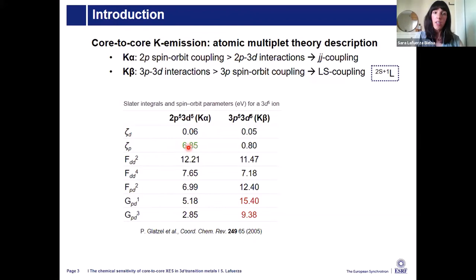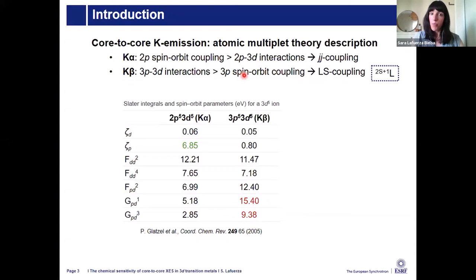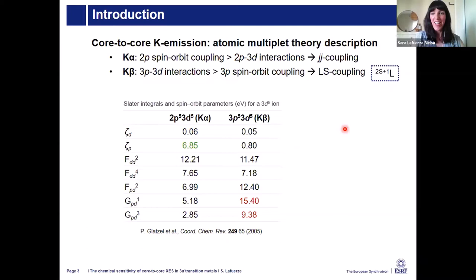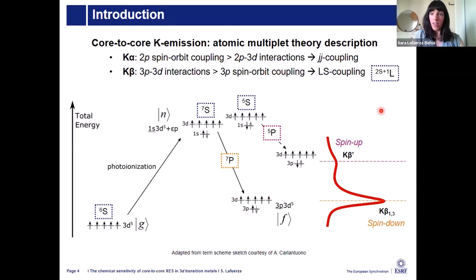In K-alpha, the 2P spin-orbit dominates over the Slater integrals. Therefore we are in the JJ coupling scheme and the spin is not a good quantum number. In the K-beta case, the 3P-3D exchange Slater integrals are dominant — much larger than the 3P spin-orbit coupling — and therefore we are in the LS coupling scheme. That means the different electronic states are well described by 2S+1 L atomic terms, where S and L are the spin and orbital angular momentum. This makes it much simpler to establish a relationship between the K-beta emission spectrum and the spin, which is why I focus on this case.